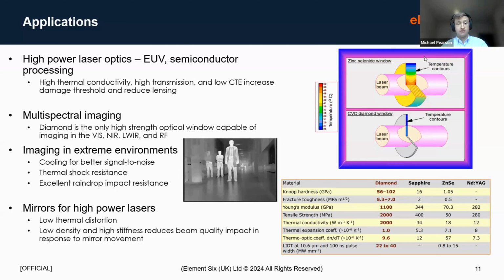And finally, mirrors for high power lasers. Again, the high thermal conductivity of diamond means that any hot spots are minimized on your mirror surface. This, in conjunction with a low diamond CTE, means that you reduce the amount of thermal distortion you get out of your mirror, improving your laser beam quality as it comes off of your mirror. That, in conjunction with the low density of diamond and high stiffness, means that you can reposition your mirror very quickly and very accurately compared to, for example, a copper mirror. Next slide, please, Ian.